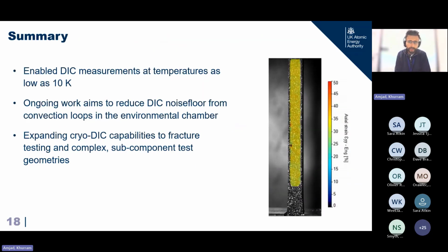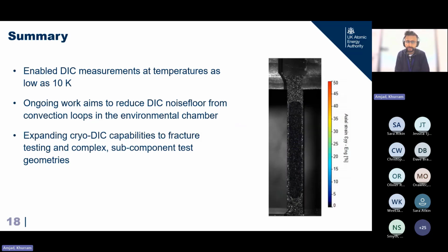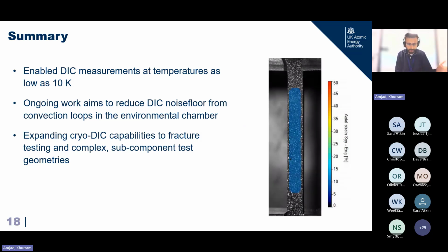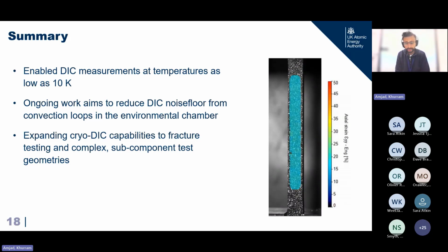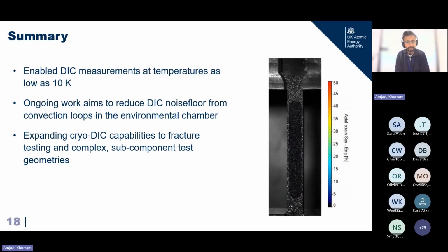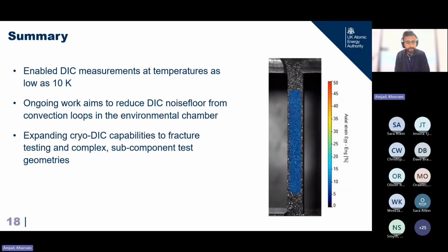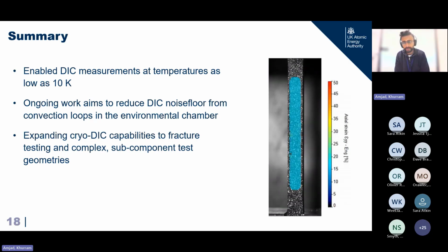To summarize, we have enabled DIC measurements at temperatures as low as 10 Kelvin. We'd also like to do it at temperatures close to 77 Kelvin in an environmental chamber, which is a much easier setup in terms of cost and time. But the DIC bit is challenging, so we are trying to mitigate the convection effects to reduce the noise floor of the measurements. And we are looking actively to expand our cryo-DIC capabilities to fracture toughness, more complex subcomponent-level test geometries, and different materials as well.